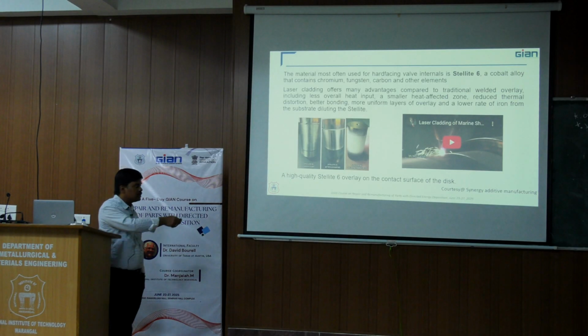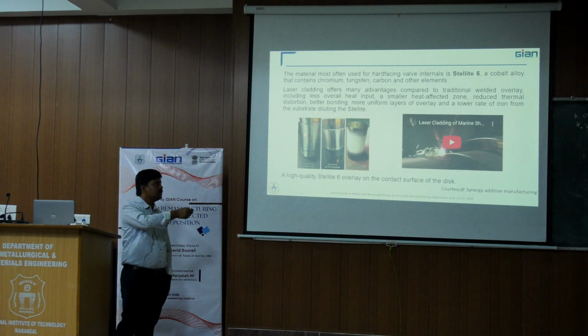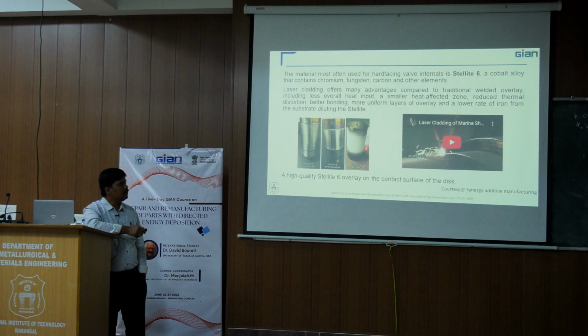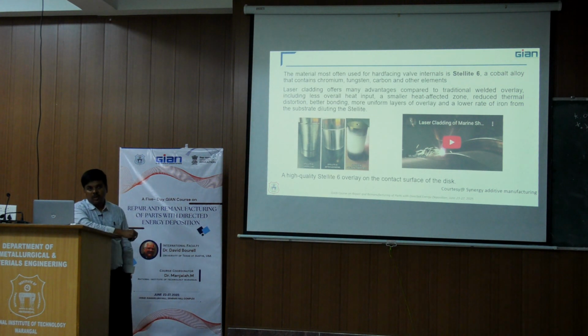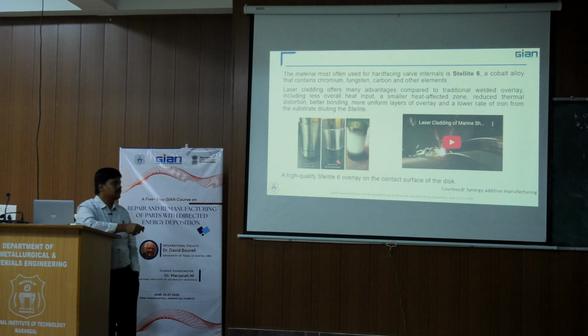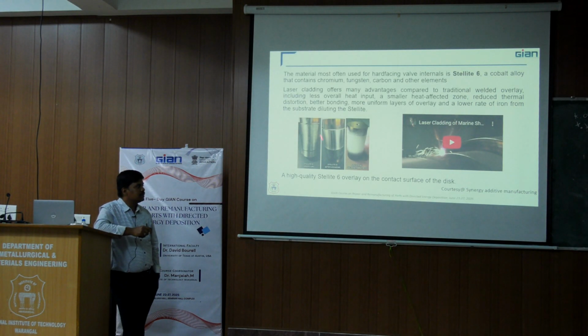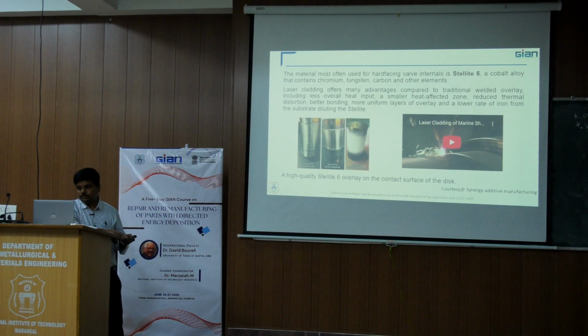Laser wire DED process, they have developed Stellite 6 on the laser cladding of the shaft, and after laser cladding they have machined it, and then they evaluated whether any kind of defects after cladding exist in that component or not. They made dye penetrant testing to evaluate the quality we are getting by the laser cladding process. This is a high quality of stellite over the surface of this disc they have done, and they got a very good quality component.